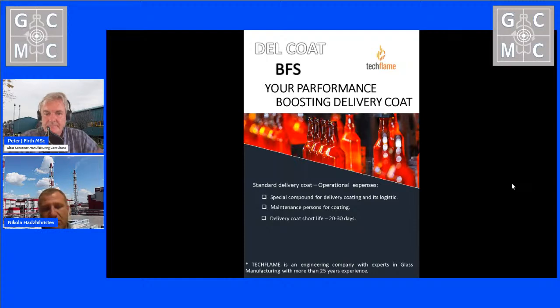As I told, and as you know, delivery coating has a short life, 20 to 30 days, and this pushes you to stop the machine for about 20 minutes to replace the whole set and run again. 20 minutes is just machine downtime, but blanks, heat hiccup, blow mold heat hiccup, all this brings you losses.